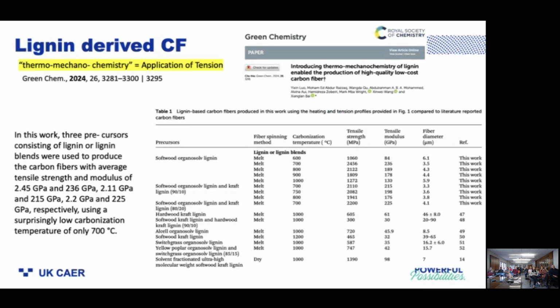Bio-derived fibers. You may recall I talked about the very first carbon fibers being produced from cellulose. The other half of the tree is essentially lignin. All of the paper processing plants make lots of lignin, which is used as a fuel in production of paper. But lignin has garnered a lot of attention over the last, I would say, 20 years, potentially as a carbon fiber precursor. I'm just highlighting one of these papers that came out rather recently. This is the first one that I've ever seen describe high strength and high modulus from a lignin-derived fiber. They talk about this stemming from applying tension, much like what was done with PAN back in the early 60s.